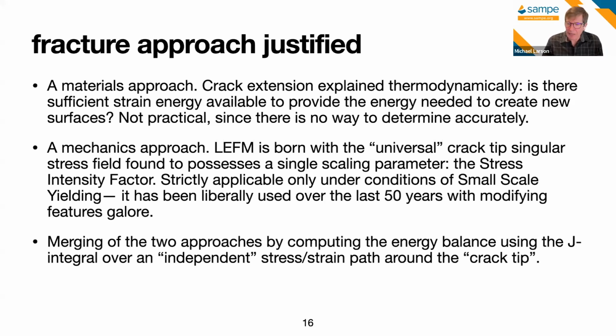We can get surface tension values from very well understood experiments, but in practice, there's a lot more going on than just the generation of new surfaces, even in what we would call ideally brittle materials. So although a very nice notion, it wasn't something that provided a lot of practical use. It then ended up in the hands of the mechanicians, the mechanical engineers, and linear elastic fracture mechanics was born when we had people like Westergaard and others that were able to identify what the stress field around the singularity of a crack tip looks like.